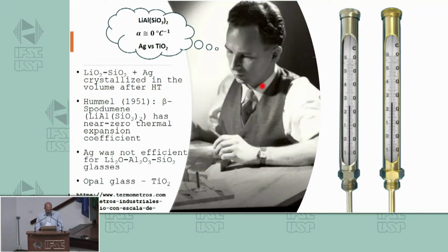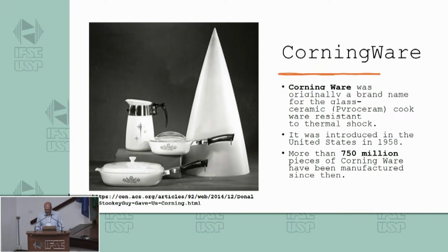But he remembered that Hummel, more or less in the same time, had described a beta-spodumene composition that had near zero thermal expansion coefficient. So he tried to bring that system, the fact that he had just discovered, but when he tried with silver, it didn't work properly. And he knew that this opal glass used in thermometers, at that time, this opal was produced by titania. And so he tried titania, and it worked perfectly. And he was able to produce then a very nice glass ceramic for the first time, and